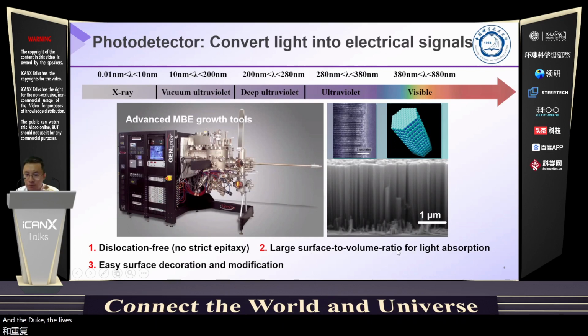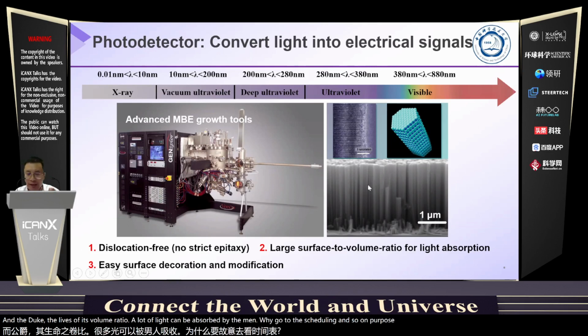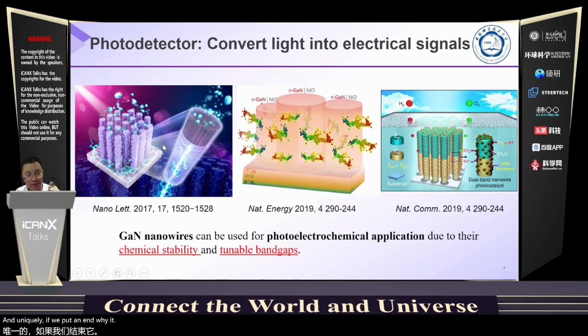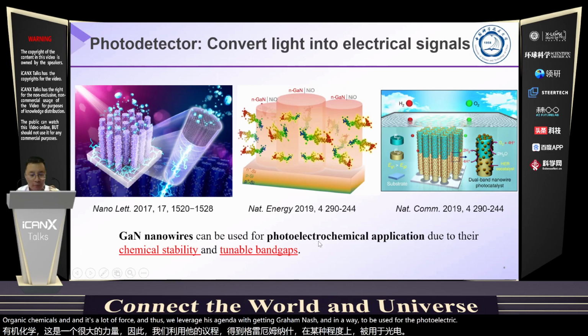And due to the large surface-to-volume ratio, a lot of light can be absorbed by the nanowires due to scattering and so on. Uniquely, if we put nanowires into an environment, because of the large surface-to-volume ratio, we are able to interact this semiconductor with liquid or electrolyte. People have demonstrated gallium nitride nanowires for water splitting, to capture carbon dioxide, to generate organic chemicals, and so on. Thus, we leverage gallium nitride nanowires for photoelectrochemical photodetectors, because gallium nitride has high chemical stability and tunable band gaps for a lot of light absorption.